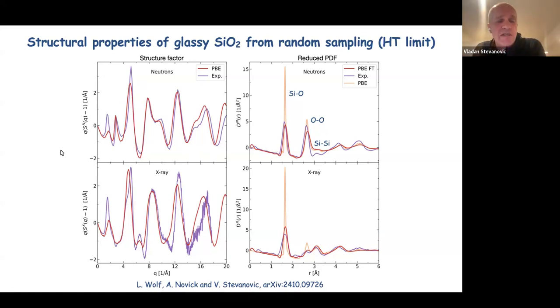So we are doing 24 atom cells. This small peak has to do with order or atom-atom correlations, if you wish, at about 10 angstroms and further. You can see from this picture that within 6-7 angstroms, the pair distribution function is again reproduced fairly well. Where this first peak enters is the density. We have about 2.5% error in interatomic distances relative to experiments, which again is expected from first principles methods.